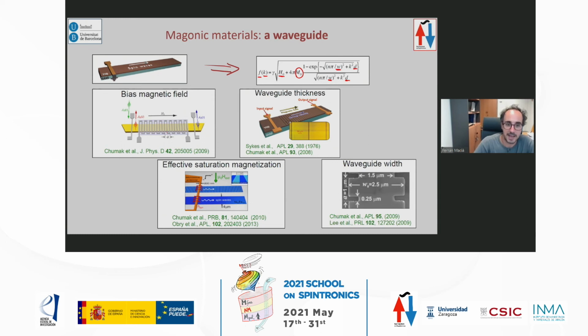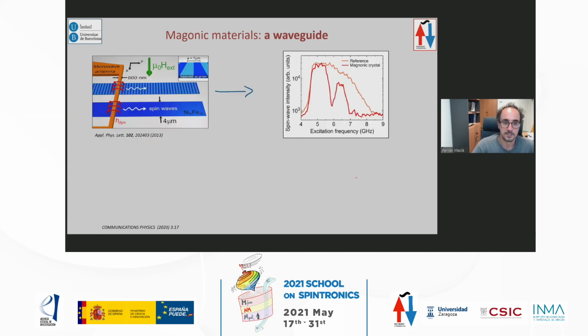So you can either change the magnetic field with some patterning of a wiring. You can change the thickness of the material by some lithography. You can change the saturation magnetization by changing the material or by implanting some ions and reducing the magnetization. And you can change the width as well, just doing some patterning. So as examples, I put you these two.